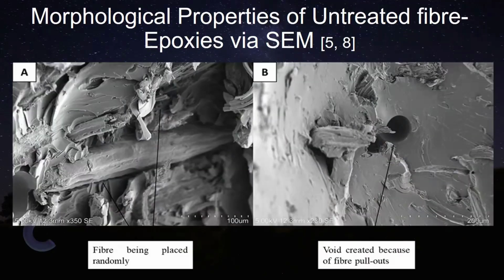From the morphological properties, when we use the untreated fiber, regardless of whatever epoxy we have used, we found that after the breaking of the sample, the fiber was placed randomly inside the resin, and therefore after the breaking, we saw that the fiber was pulled out, and because of the pulling out, there is a void creation, and that is the indication of the not so good or poor fiber matrix adhesion property.